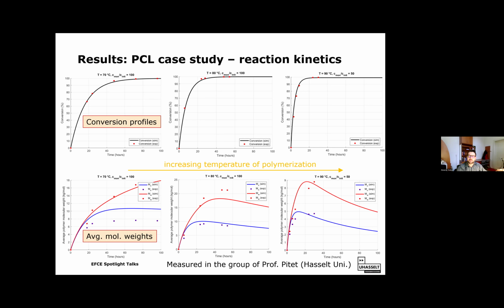You see from the conversion profiles that, as we expect, the rate of the polymerization increases with increasing temperature. The agreement between predictions and experimental data is excellent, at least in the conversion profiles. It doesn't look that excellent when we look at the molecular weights, but there is still work going on, and we're thinking about expanding the polymerization scheme a little bit. But overall, even the molecular weight predictions look, in our opinion, definitely better than what we have seen so far in the literature regarding the kinetic modeling of polycaprolactone. So not that bad, hopefully.